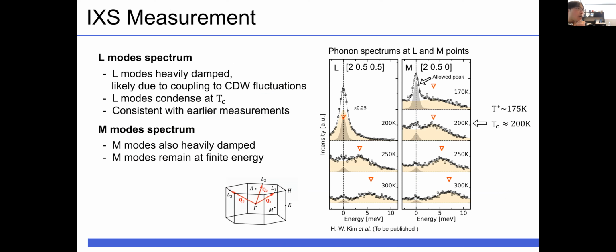And here are our observations. Generally, phonons have very long lifetimes, and the phonon spectrum should be the same as the instrumental resolution, like the elastic signal at 0 energy, the gray area. However, the L phonon in the orange color has a very broad line shape from room temperature to the critical temperature. It's likely because the L phonon is coupled with charge fluctuation, and the energy of L modes goes to 0 at the critical temperature, 200 Kelvin. These are consistent with the earlier measurement.